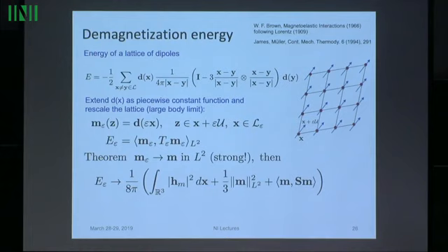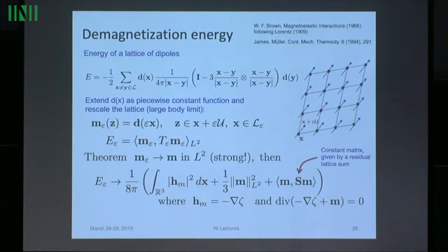And if M epsilon converges to M strongly, then you get this formula, and this is exactly the demagnetization term I had earlier. This is typically a constant in ferromagnetism because it has constant length. The length of the magnetization vector is taken as constant. This is a lattice sum that really does come out of homogenization. It's usually lumped in with other terms in the energy. So this is the exact formula you get. And you also get the differential equation.